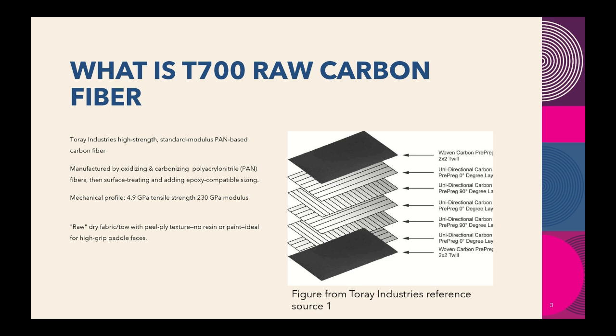T700 raw carbon is a high-strength standard modulus material developed by Toray Industries. It's made by processing PAN fibers, which is polyacrylonitrile, through a sequence of oxidation, carbonization, and surface treatment, followed by coating the fibers with epoxy-compatible sizing. T700 has a tensile strength of about 4.9 gigapascals and a modulus of around 230 gigapascals, meaning it's both very strong and stiff, but it's not too stiff where it becomes brittle, similar to T800 and T1000, which are very expensive and very fragile materials, making them not great for pickleball paddles.